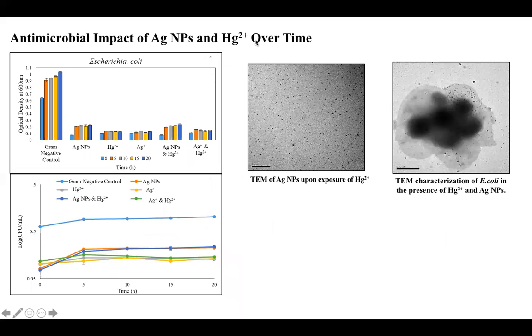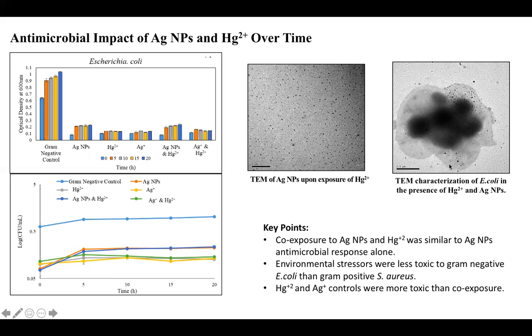Okay. And then even in the presence of E. coli, but still pretty toxic as a whole. We do see that in co-exposure to both of these, we still see that same behavior that occurred the first time. Okay, so that changes how these things are growing and how they're concentrating at the cell. And if we look at this TEM image, again, we can see it concentrated on certain areas of how it's distorted the bacteria, indicating that cell damage is occurring and it's starting to break down over time.